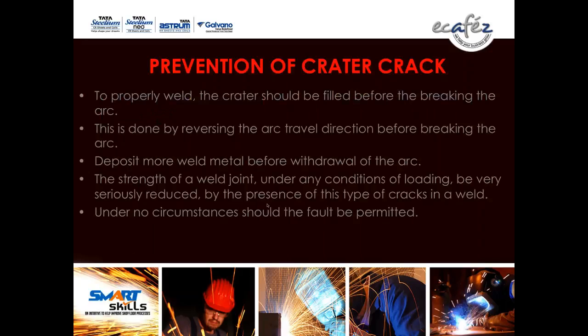Prevention of crater crack: to weld properly, the crater should be filled before breaking the arc. This is done by reversing the arc travel direction before breaking the arc. Deposit more weld metal before withdrawal of the arc. The strength of the weld joint under any conditions of loading is very seriously reduced by the presence of this type of crack in a weld. Under no circumstances should the fault be permitted.